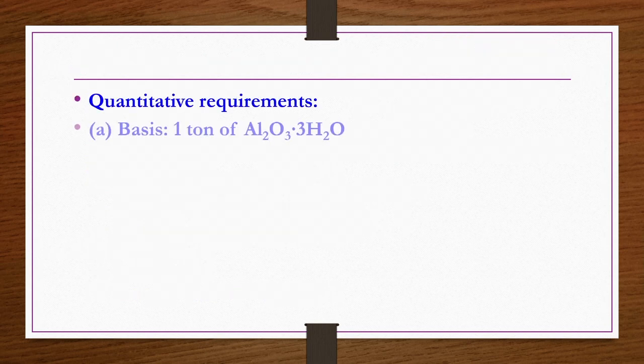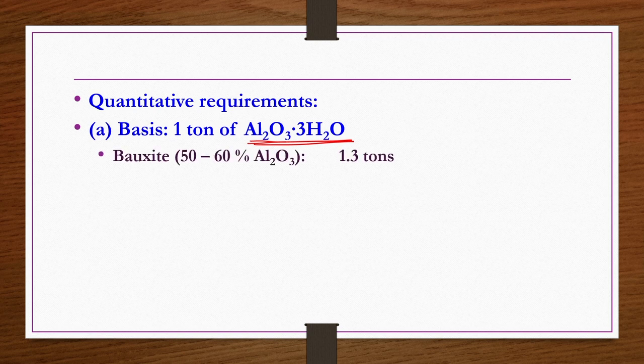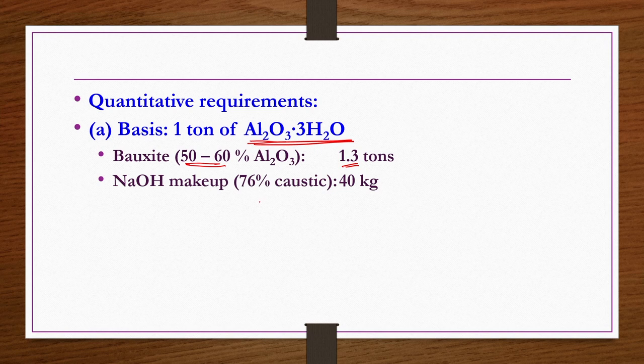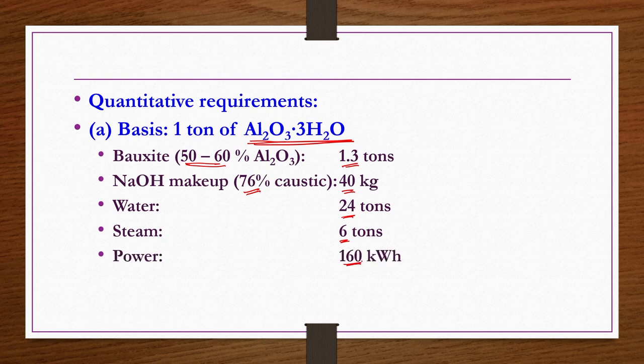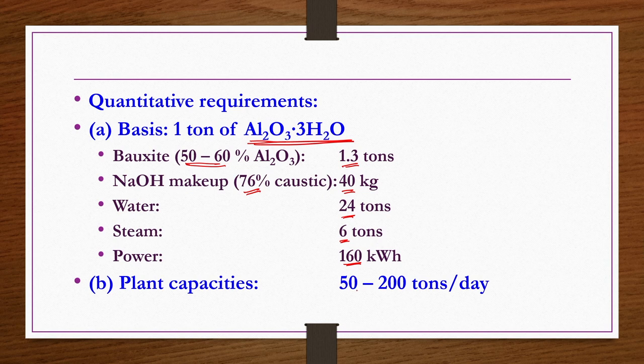Quantitative requirements: the basis is, if you wanted to produce 1 ton of trihydrated alumina, that is Al2O3 3H2O, then you need 1.3 tons of bauxite ore containing 50% to 60% Al2O3. NaOH makeup solution, which is 76% purity, 40 kgs is required. Then water is required, 24 tons. Steam, 6 tons required. Power, 160 kilowatt hours required. Plant capacity is usually 50 to 200 tons per day.